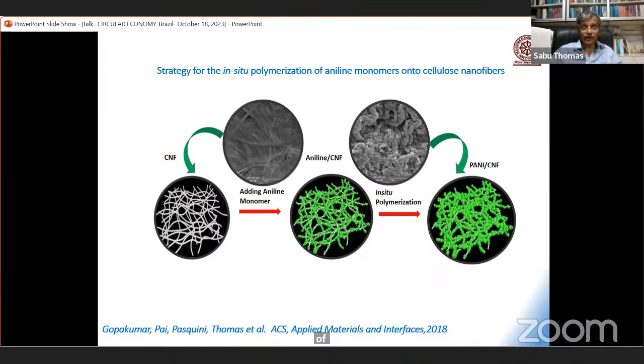You can make beautiful aerogels out of nanocellulose. I wanted to cite the work of Mr. Gopakumar Pai. Gopakumar made nanocellulose from the stem, then he introduced aniline, then he went for in-situ polymerization of aniline. And he made an aerogel of nanocellulose. When you add aniline and CNF, this is the morphology, and this is the aerogel.